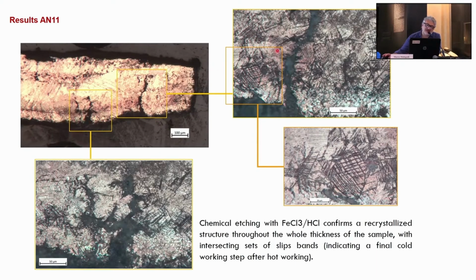And as you can see, we could have this kind of magnification in this chemical etching with ferric chloride/hydrochloric acid, just to confirm a recrystallization process here in the whole thickness of the sample. And the signs that you can see here are the signs of this process of recrystallization that indicate a final cold working step after a hot working.